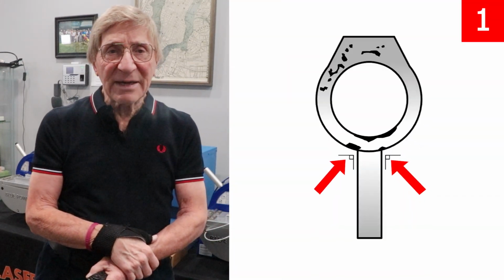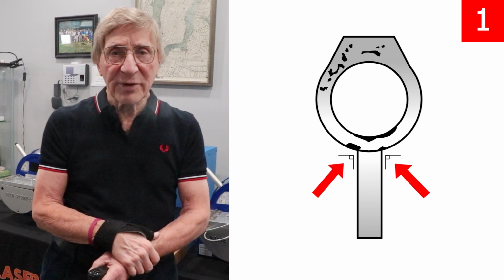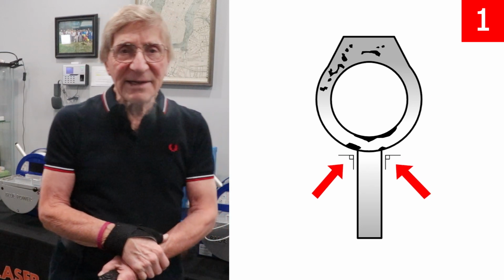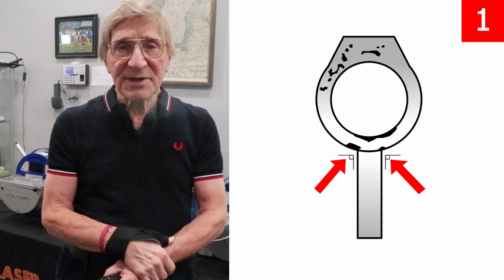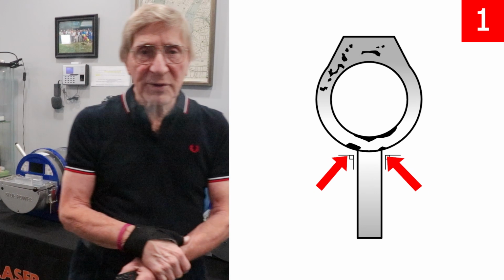The following illustrations you're about to see indicate some common casting issues. Diagram 1 shows the incorrect way for a sprue to enter a ring. It shows 90-degree corners as indicated by the arrows. When the metal enters this ring, a certain amount of turbulence will be created. This will result in a pickup of air which is being introduced into the ring cavity.